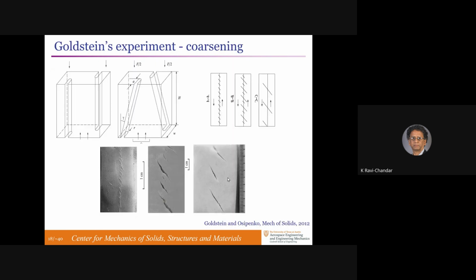The next thing that happens is that the daughter cracks grow, but they shield one another from growing, and they lead to what is called coarsening. Goldstein did some experiments in the 2000s, I think, where he took a specimen, which is where we got our designs for the threshold determination. There are cracks on two sides, asymmetric, either tilted or straight, under 3-point bending. So they have this mode 1+3 loading, and they spawn daughter cracks.